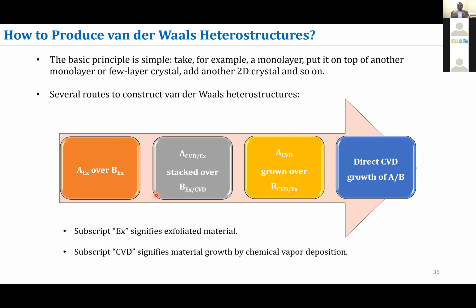Here there are different ways you can create heterostructures. For example, if you are taking graphite and a piece of bulk boron nitride, then you can exfoliate using the scotch tape that I discussed in the beginning. You can use scotch tape to take a layer of graphene and put it on silicon oxide, and take a layer of boron nitride and put it on top of it. So you can create a heterostructure using the simple scotch tape process. Also, you can grow a layer of boron nitride first on a metal film, or directly on silicon oxide or a dielectric substrate, and then scotch tape graphene and put it on the boron nitride that is already prepared on the dielectric substrate. Or we can create both graphene and boron nitride directly using a CVD process, where we can completely avoid all the transfer-related steps.